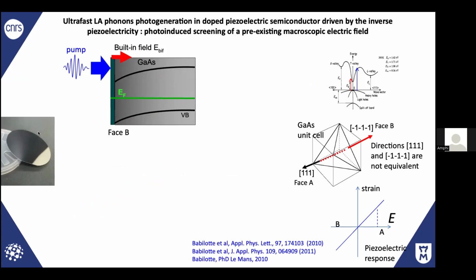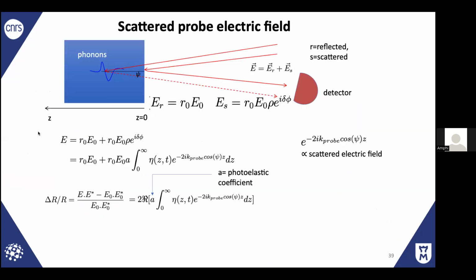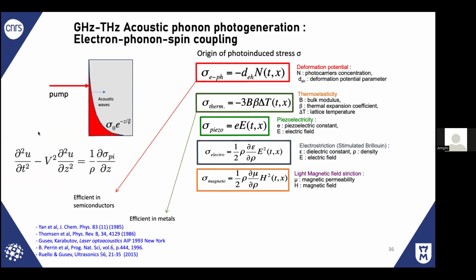For the light polarization, of course, I would just like to come back to that situation. The light polarization will be important to define the quantity of electron hole pairs you have created if it's a birefringent material. So that will govern the value of n. The value of n will also control the value of the temperature, because if you absorb more, you will heat more. The same way, the transient electric field, as I explained to you, is also related to the quantity of electron hole you have injected to screen the field. So always ordinary or extraordinary.